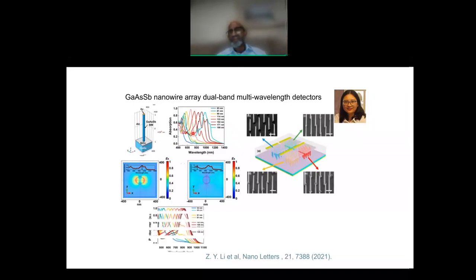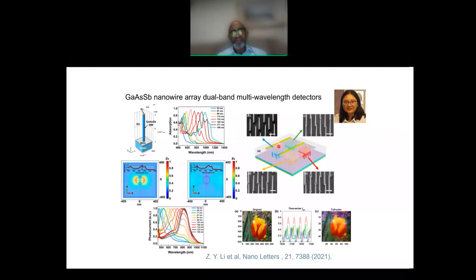Then she fabricated four different kinds of nanowires of different diameters, and of course not a single nanowire but multiple nanowires. You can see the actually measured ones, and they're very much comparable to what we simulated. In fact, we have taken an original image, and using our detector, we were able to do a full color image of these particular structures. Again, this work has been published this year, and Xiong and many students and colleagues have been involved.